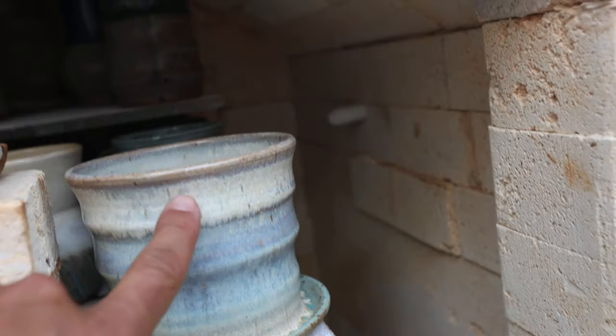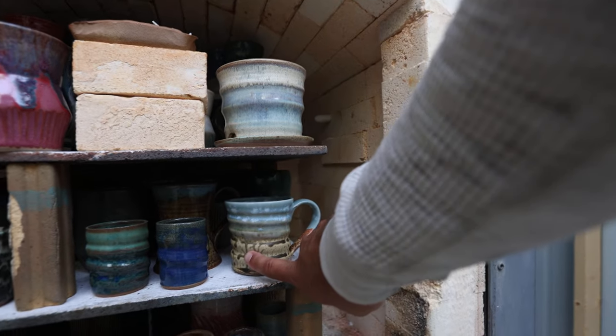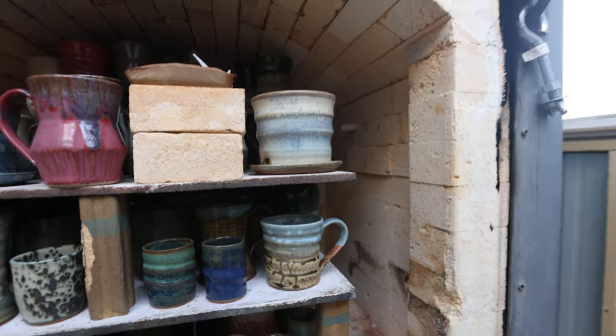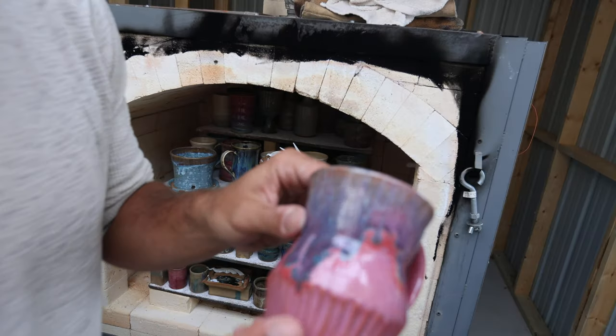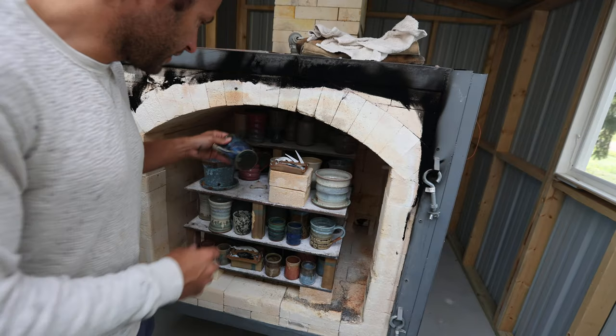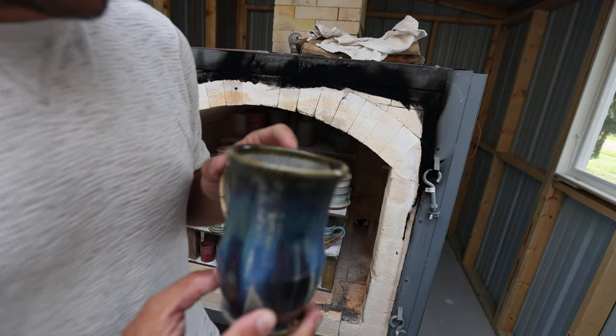Celadon Bloom, and this is Sand Dollar over Riptide. I'm super excited about this ash glaze — it's a wood ash glaze, just 50% wood ash and 50% Red Art, sprayed on. There are tons of pots in here, it's going to take us a little while to unload. Unfortunately this one did have a cone drip on it. This is 'Insanity' refired in the gas kiln.